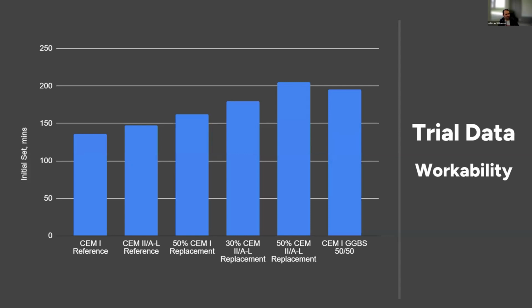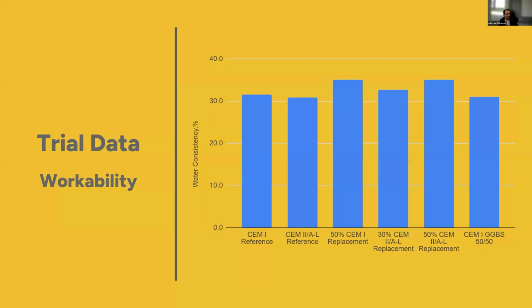Workability, in a similar fashion, and initial setting times, nothing too out of the way. We're seeing a 50% CEM1 replacement is actually very similar to our reference CEM2 cements. Water demand, kind of a problem that's known with calcined clays, but again, seeing no major concerns there. Things we can work on, things we can tweak and refine. But for us, for a first attempt at this at scale, something we were pleasantly surprised by.